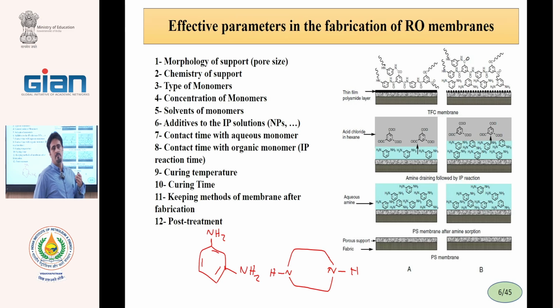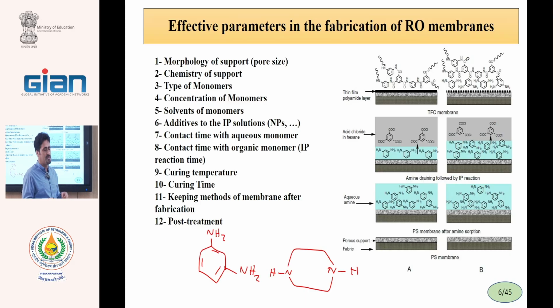And now, in a membrane fabrication factory, they use 30 seconds for contact of MPD with the support. In lab, we usually use 5 minutes, but in industry, 30 seconds. With addition of surfactant, for example, surfactant to the aqueous solution, the diffusion rate of MPD into the pores increases. The surfactant reduces the surface tension of the solvent, and the MPD diffuses rapidly, and the production time of the RO membrane reduces. Therefore, we can change the kinetic and thermodynamic condition of this reaction and reduce the time and increase the flux, increase the permeability.